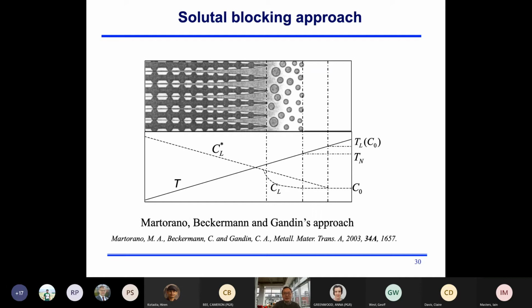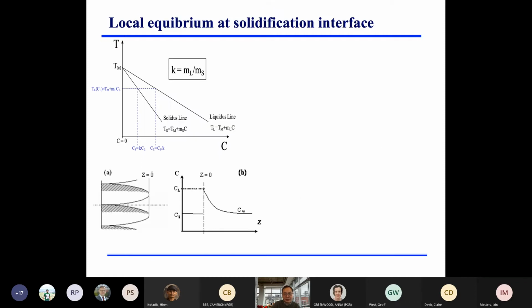Yeah, we use something called a solute blocking approach. Here is the dendrite solid phase, and this is the liquid phase. For example, we grow dendrites from the left hand side to the right hand side, and look at the solidification interface. Most alloys have alloy components, and normally we use a partition coefficient less than 1. For example, aluminum copper, nickel aluminum, iron carbon systems all have alloy elements with partition coefficient less than 1. So you get an enriched layer of solute elements, and how can this affect solidification morphologies, right?